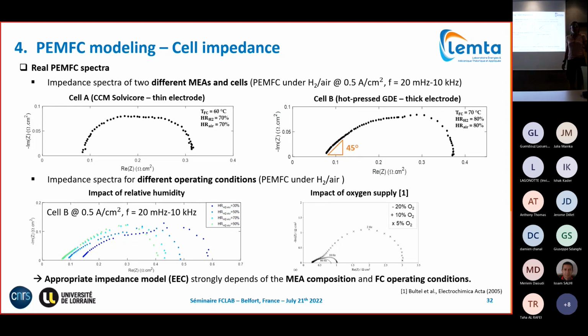This means the higher your relative humidity, the lower the membrane resistance. The higher the humidity, the lower is the value of the resistance, the real intercept of your spectrum with the real axis. And it will as well depend on your oxygen supply.